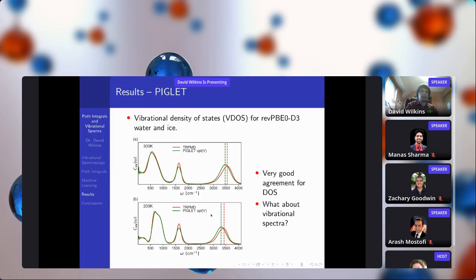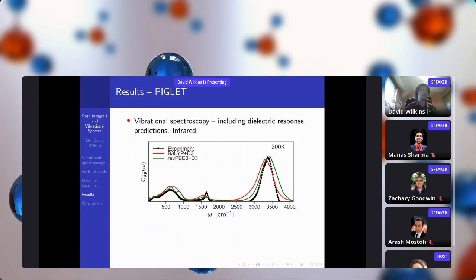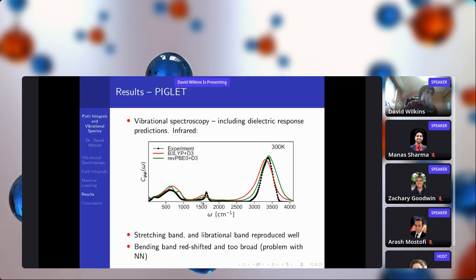So, sorry, my mouse is going crazy. So given this, let's combine the vibrational dynamics, which we're doing pretty well at, with the responses and get some vibrational spectra. And here we have the infrared spectra of water, where we include the dielectric response and the vibrations. And you see that at both these levels of neural network, we're doing reasonably well. The OH stretch is pretty good. The librational modes at low frequencies are also pretty good. The main problem is this bending mode at the mid-frequency range. And I can happily tell you that this isn't a problem with the symmetry adapted model that I trained. It's actually a known problem with the neural networks. They do slightly redshift and broaden this band. So that's the reason why it's not perfect with spectra.